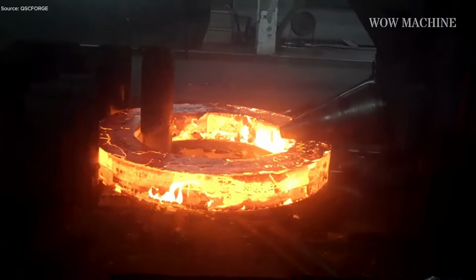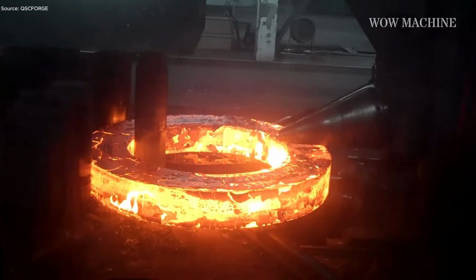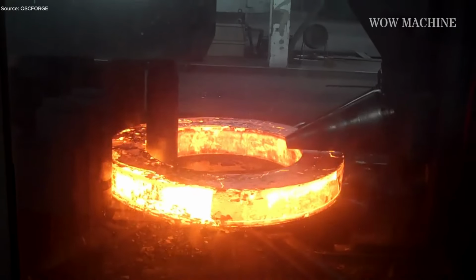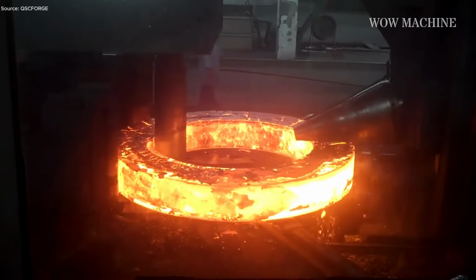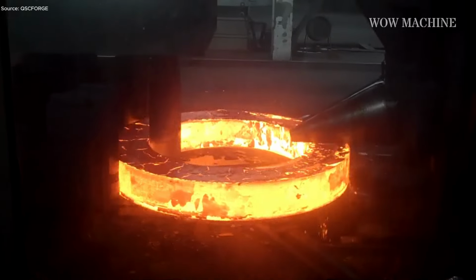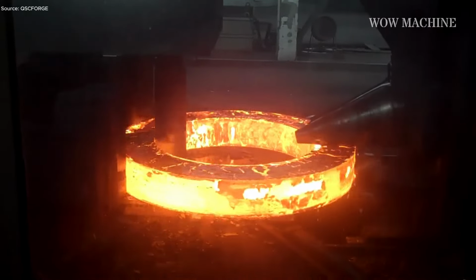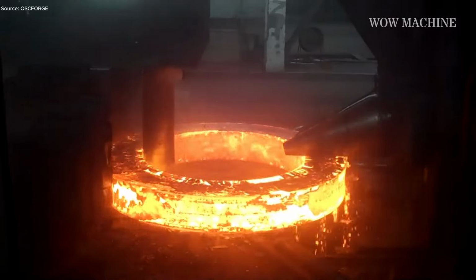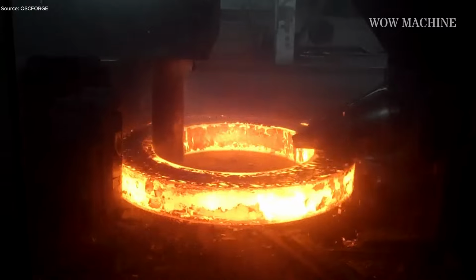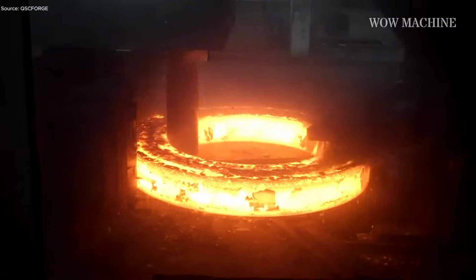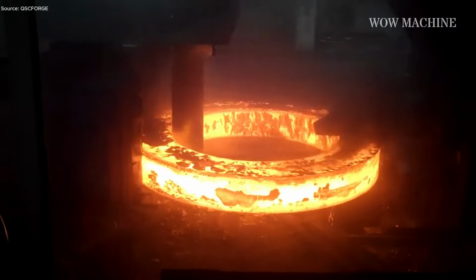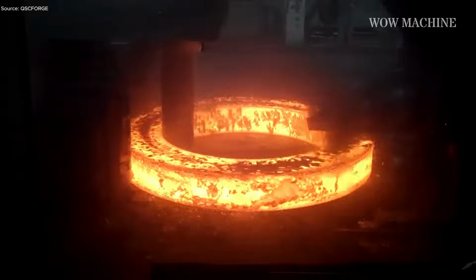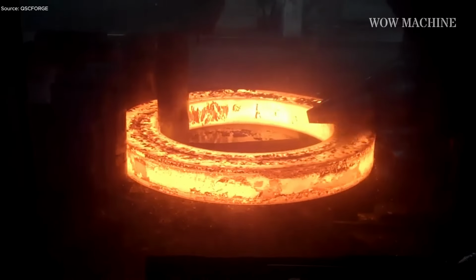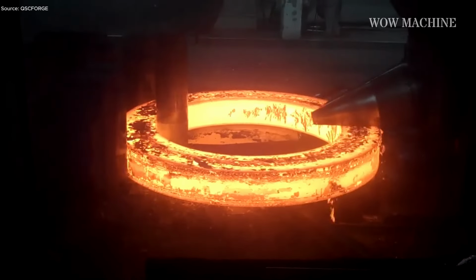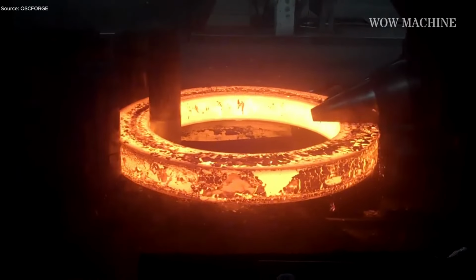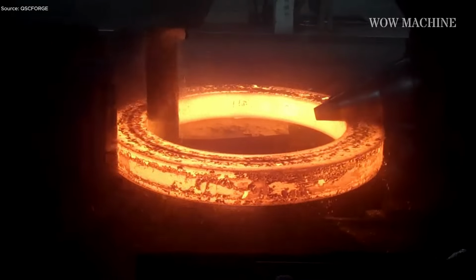At the ring mill, rollers stretch the metal outward while thinning its wall, gradually expanding it to its required diameter. Operators control both rotation speed and pressure with tight precision. Each adjustment of pressure translates directly into millimeter changes in diameter. That's how sensitive this process is. The hydraulic press communicates in pressure curves, not words. Even a small temperature dip can ruin the balance, so timing is everything. Blink once and the ring's already grown a full size. That much steel moves like clay under the right force.